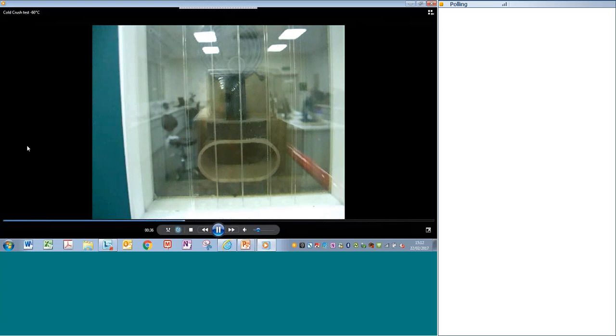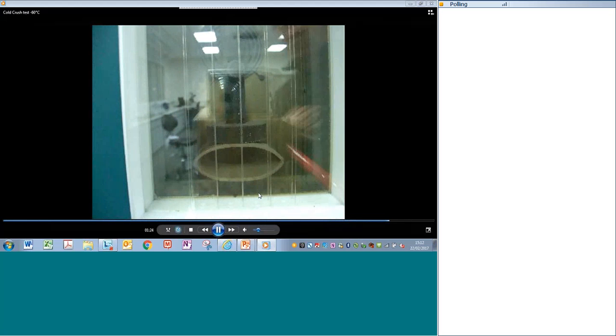And this kind of test is one which we employ to demonstrate clearly that we are manufacturing pipes of the required ductility for the application. And if I just accelerate this a little bit for you, you'll see that as the pipe is compressed at a fairly fast rate, we reach a point where, in fact, both opposing faces actually come to touch, and there will, of course, be some yielding at the edges. But when the load is released, you'll see that the pipe recovers quite substantially